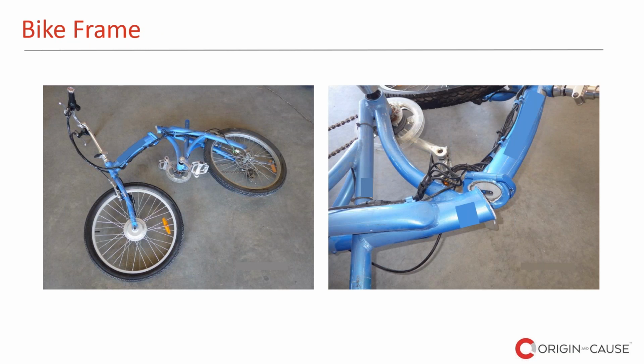The next case involves a personal injury which occurred as the result of a bike frame failure. As you can see on the right side image, it was the main frame that broke at the weld. Like in other cases where there are multiple parties involved, we organized the joint destructive examinations. We prepared the testing protocol, which was discussed with all the parties in advance, and we accepted suggestions or modifications if they were reasonable.